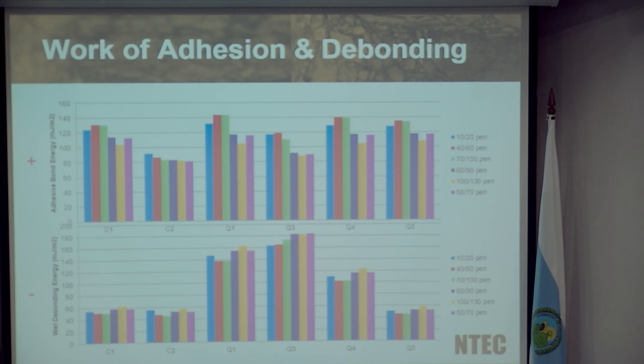So dry adhesion tends to be fairly standard. If you keep everything nice and dry, as you would expect in an asphalt mixture, your performance is going to be very similar. There will be subtle differences in terms of changing the type of binder, changing the aggregate gradation, changing potentially the source of the aggregate. But your performance should be pretty similar. It's when we introduce that water into the equation that we start to see big differences.